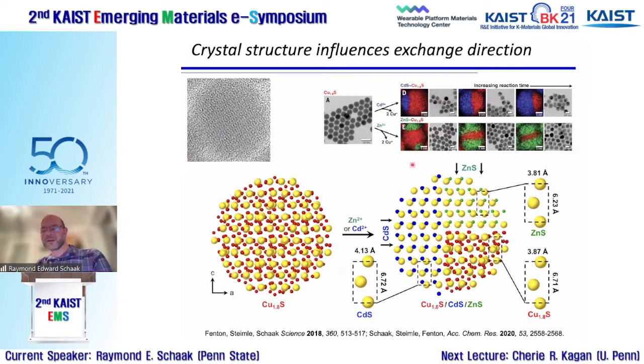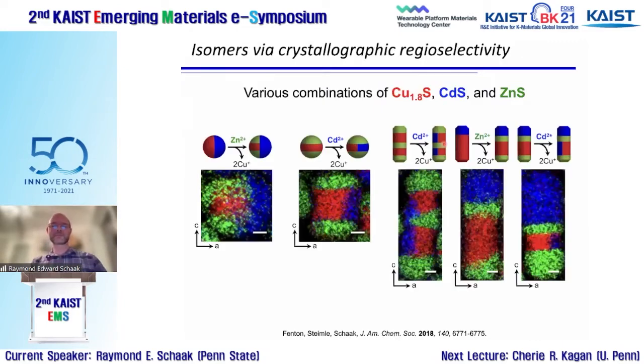And so the end result is that the orientations that I'm showing here actually match the crystallographic orientation. So cadmium in a single crystal of copper sulfide that's oriented this way, cadmium will tend to exchange and diffuse in from the side and form an interface this way, where zinc will come this way. And so that becomes really powerful because that lets us start taking, let's say, a spherical object and breaking the symmetry and doing reactions inside the particle that are precise, really precise in their location.